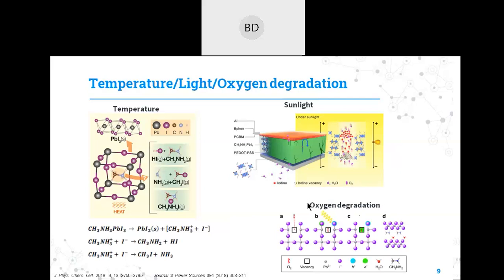But when it is coming in combination with sunlight, it has a very detrimental effect on the perovskite structure. If you see here, these iodine vacancies are present in the case of sunlight exposure. And in the oxygen exposure also, the oxygen can take up these vacancies. So once the oxygen comes to this vacancy here, it starts eating up the charges.